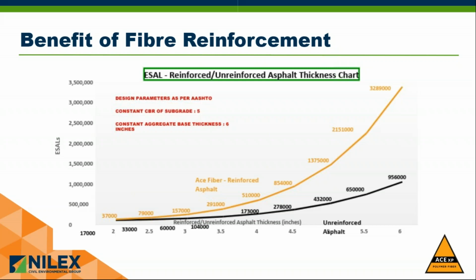So what this chart is showing, if we take a pavement design, 150 millimeters of aggregate base on a competent subgrade CBR5, if we vary the thickness of the asphalt and compare an unreinforced mix to a reinforced mix, what we're able to do by adding the fibers is actually adjust, in the AASHTO 93 design method, the layer coefficient for the asphalt layer. So typically, we're using between 0.4, 0.42 in Canada. We can bump this up to 0.5, 0.52, so a 30% increase.